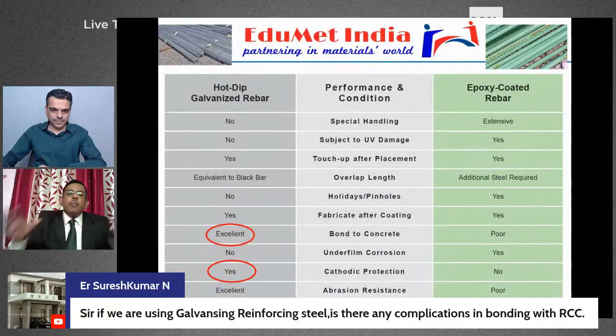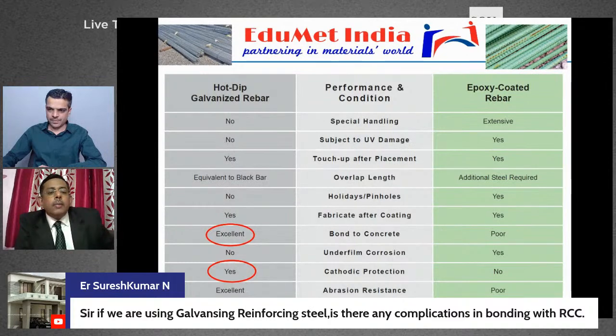So you see that it is a comparison between epoxy coated rebars and hot dip galvanized rebars. You will get most of the conditions better. Bond to concrete, cathodic protection, everything is far better than the normal or epoxy coated rebar. I have the reference for these slides. It is from the American Galvanizers Association. I think that gives a clear idea of what sort of improvement we can expect from galvanized rebars over the epoxy coated or normal rebar. Is it okay? Yes.